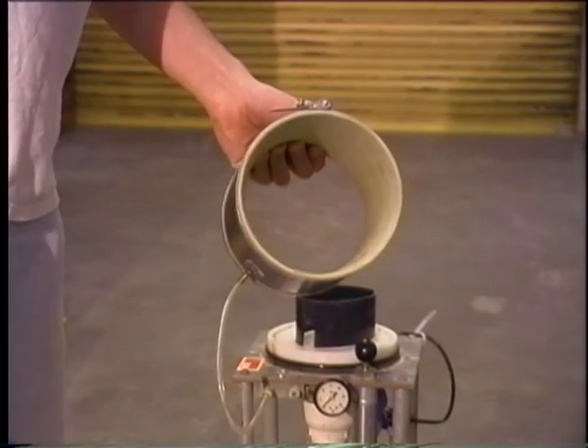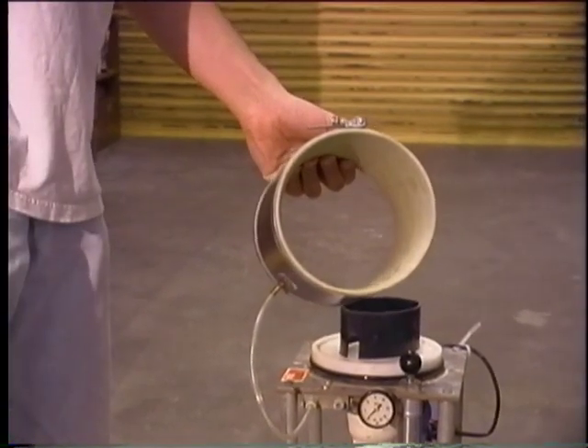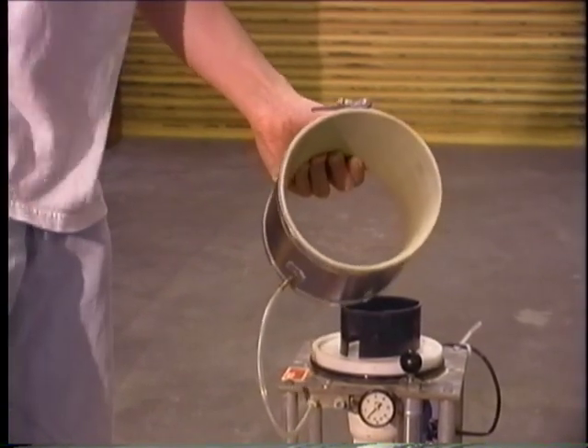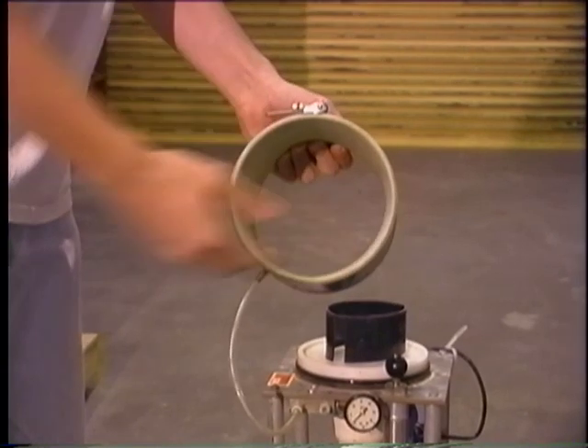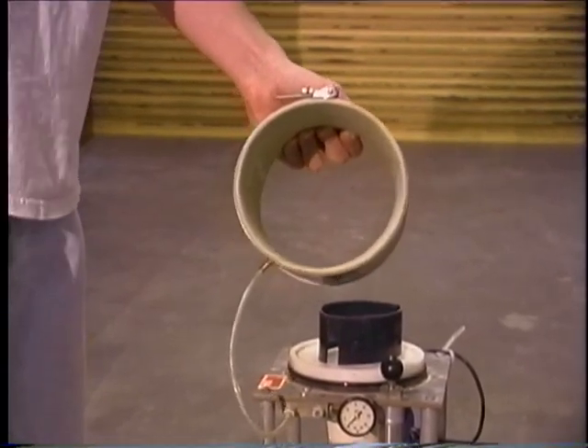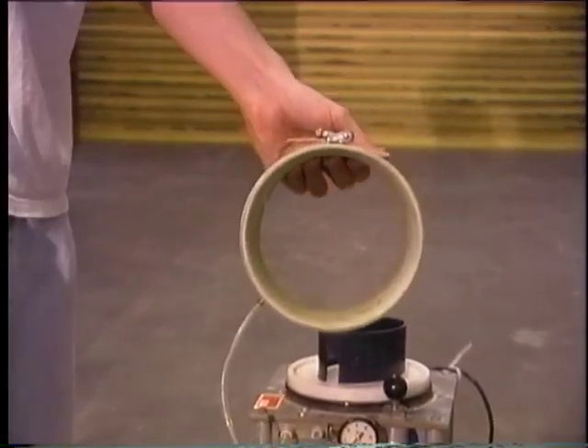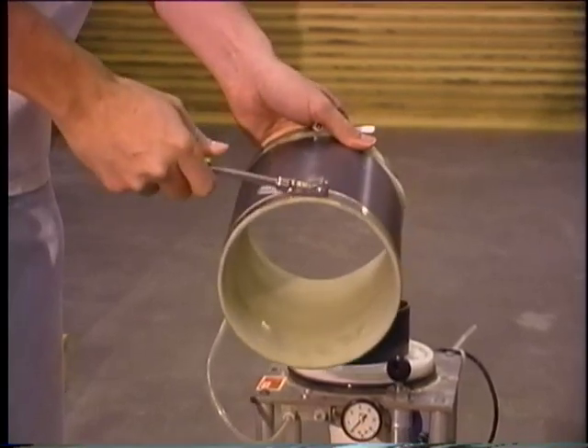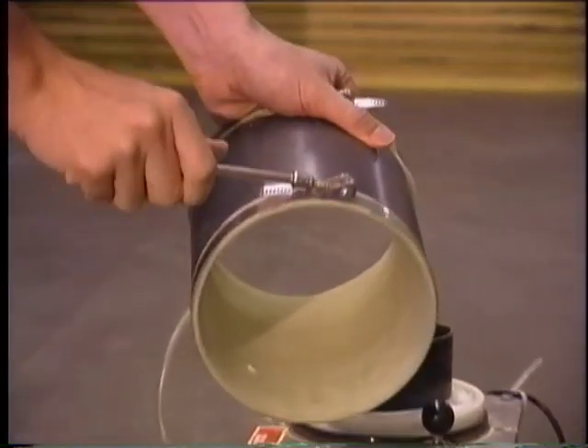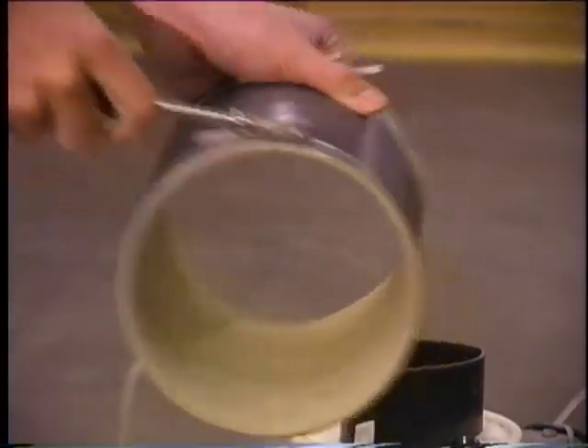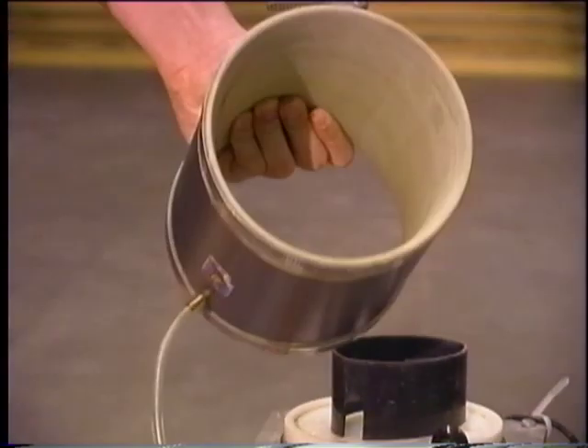The inside of the chamber in which the test specimens are placed is covered by a flexible membrane. During testing, this membrane is pressurized, forcing it against the sides of the test specimen. This prevents water from flowing along the sides of the specimen and forces water to flow only through the specimen. If water is allowed to flow past the sides, the data will be inaccurate.